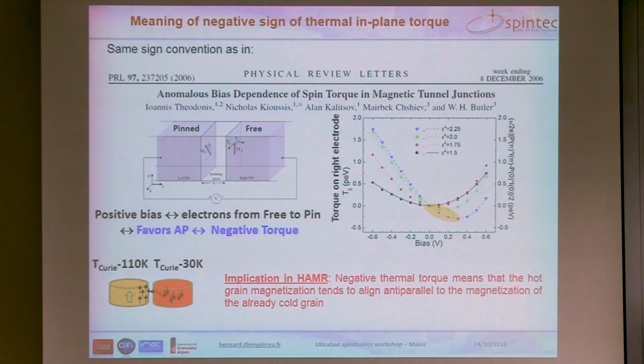What having a negative torque means is that we are using the same sign convention as in this paper, in which we calculated this torque in magnetic tunnel junction. And if we look at a positive bias here, electrons are actually tunneling from free to pin layer. And we know that in magnetic tunnel junction, if the electrons are tunneling from free to pin layer, this favors anti-parallel alignment.